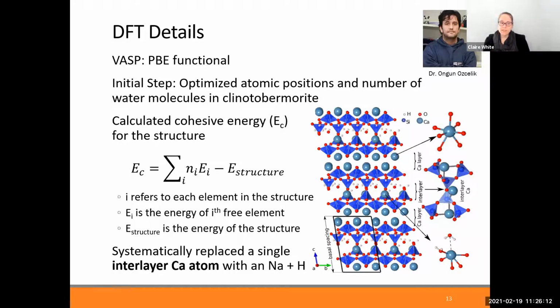And so what we did was we systematically replaced single interlayer calcium atoms with not just sodium atoms, but also hydrogen, because a previous investigation we did on tobermorite, on the replacement of calciums for sodium, found that if you charge balance not with two sodiums, but instead with a sodium and a hydrogen atom that turns into a hydroxyl, that makes the structure more energetically favorable compared to two sodiums by themselves. And so what exactly we're doing here is, this is the interlayer region in clinotobermorite. So we were taking superstructures of clinotobermorite and systematically replacing calciums for sodium and hydrogen atoms.